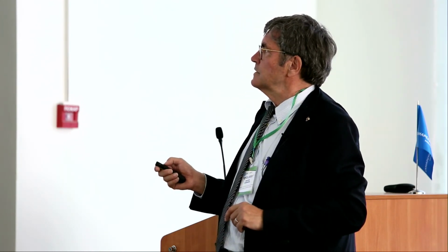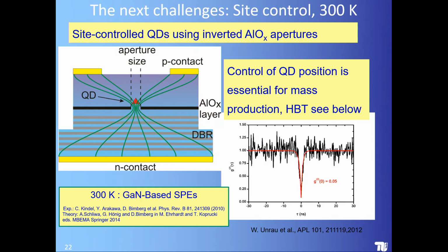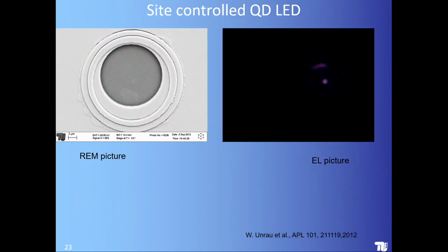And suddenly we found a possibility to control the quantum dot position, which is essential for mass production. And you can do the same at 300 Kelvin actually, making gallium nitride based single photon emitters. And what you see here now is the result of a Hanbury Brown and Twiss setup, which tells you that really the second order correlation function goes to 0 at the point when the quantum dot, the qubit, is emitted. And here you see now the picture of the device, and you see that the light exactly comes out from the center of the device.